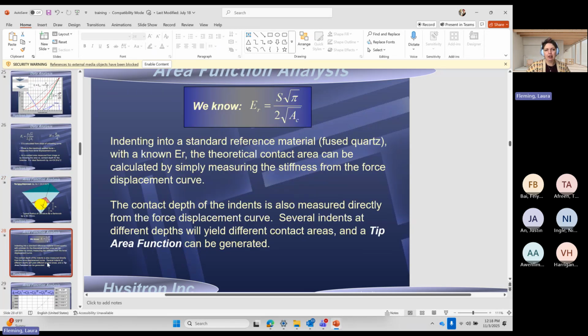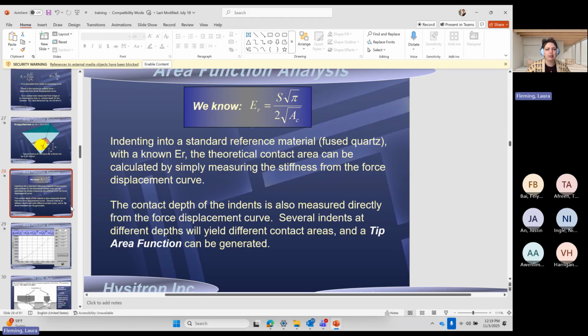How can we fix that? So what we say instead is, wait, I have a sample that has a really well-known, well-defined reduced modulus of 69.6 that is constant as a function of depth. It doesn't have surface irregularities. It's well-known, well-defined, well-proven, and that's fused quartz. So what we do is we instead do an indent into the fused quartz and we switch this equation all around. We say, okay, well, the stiffness, I'm getting that from the graph, that information I have. I know what this reduced modulus should be, 69.6. So let's go ahead and solve for the contact area at this depth. And if you do it over and over and over again, you can start to define that tip area function. So this is all handled through the software, but we should understand where this is coming from.